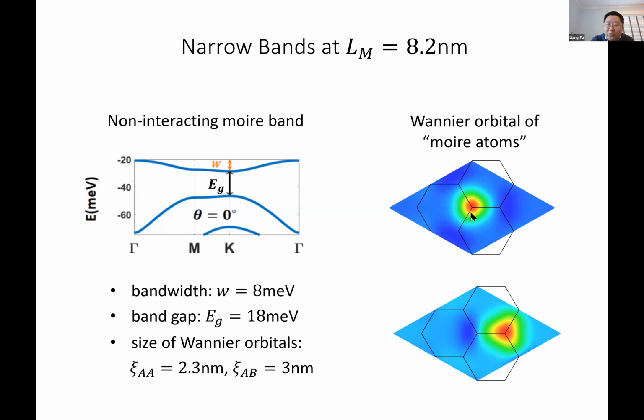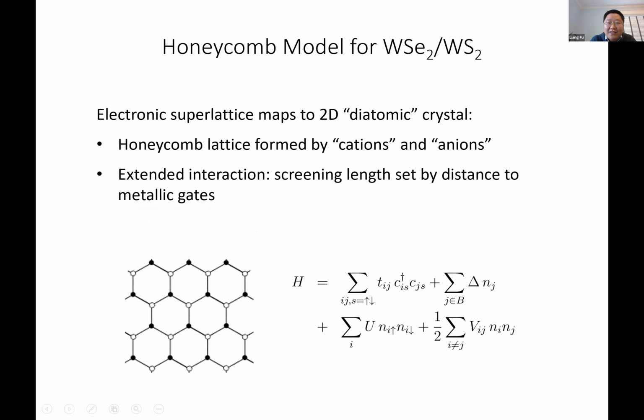So really, what we should think is that although this Moiré material has 10,000 atoms per unit cell, in terms of its low energy electronic property, one should just think of it as being like a diatomic crystal. There's one type of atom in the AA region, it has an S wave-like Wannier orbital, and there's another set of atoms in the AB region. And if you take these two atoms together, they span a honeycomb lattice. So this gives us our low energy description.